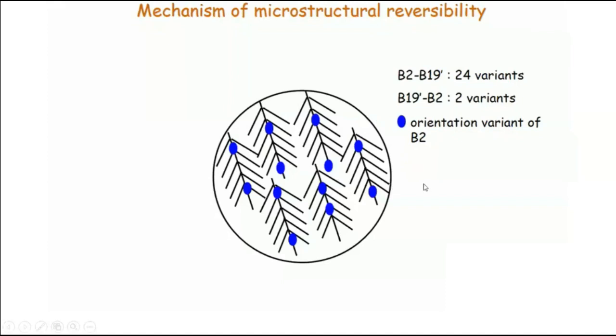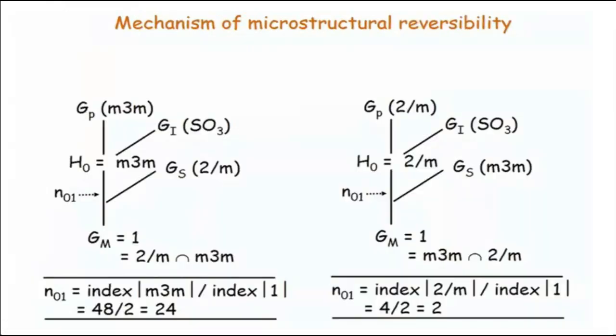Otherwise, you'll get irreversibility, or you'll get a grain refinement, as you see in steel more popularly. So how does it do it? There has to be some kind of a restriction on the way this interfaces, that it should give rise to, even across space, that the orientation remains the same.